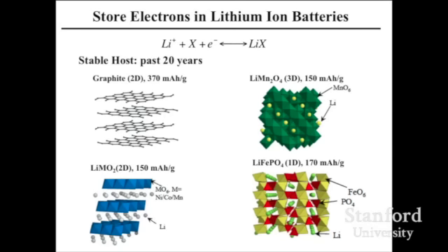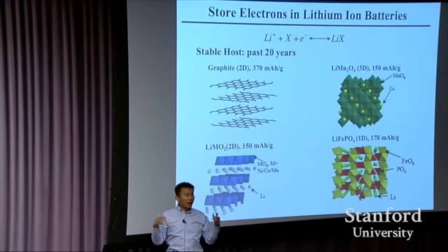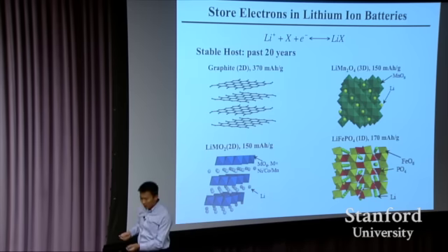You need to have stable hosts to host electrons and ions. So graphite is for the anode, 370 mAh per gram. Lithium manganese oxide, layered-structure lithium metal oxide, lithium iron phosphate: more or less 150, 170 mAh per gram. We can do this back and forth. In one-dimensional, two-dimensional, and 3D space, hosts allow ions to come in and electrons to come in and meet right there without a big structure change or volume expansion. So you can do this 500 cycles, 1,000 cycles also.